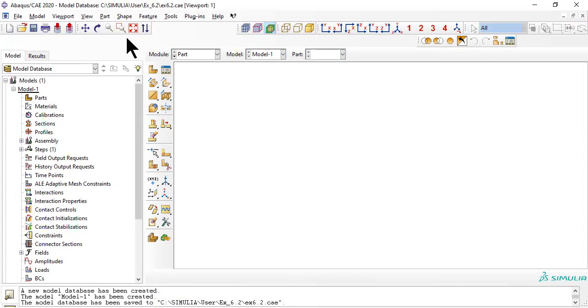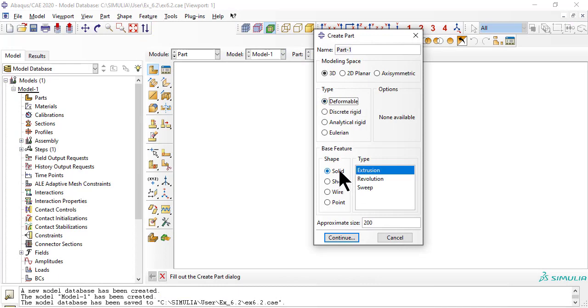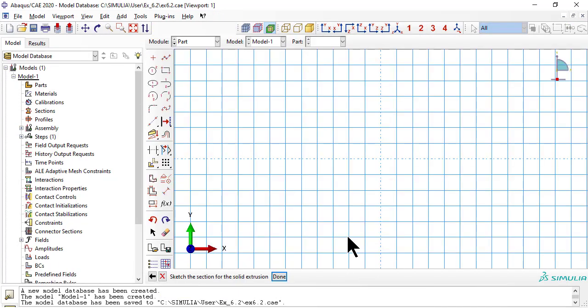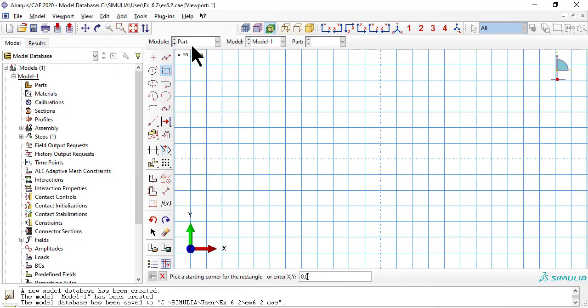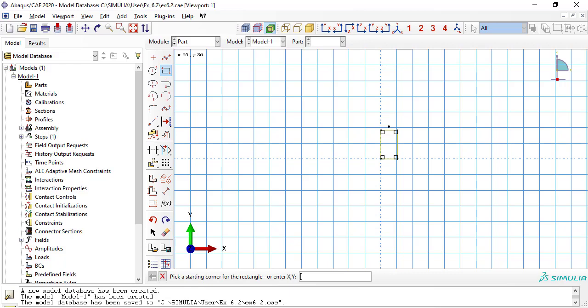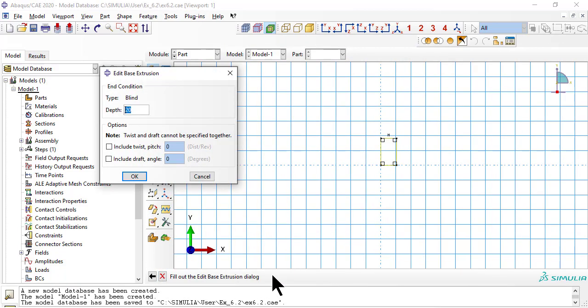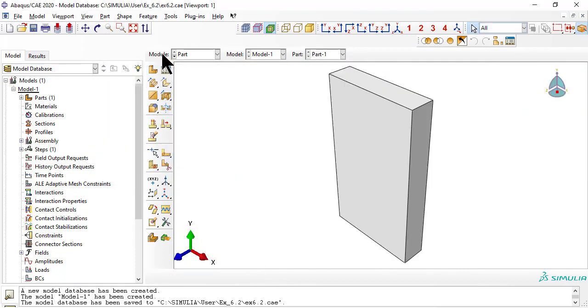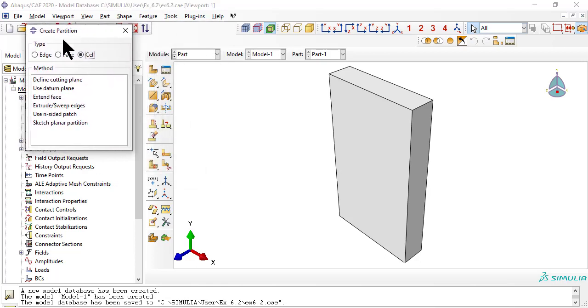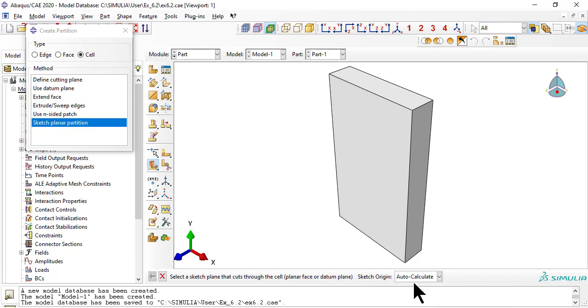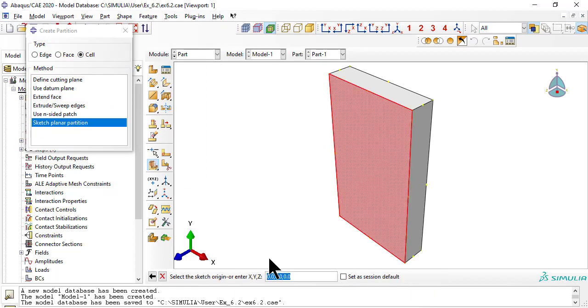To build the part we start with 3D solid extrusion. On the XY plane, we draw a rectangle with dimensions width times height of the RVE, and extrude it with a depth equal to the depth of the RVE along the fiber direction. Now we partition the front face of the cell with a sketch of the cross section of the fibers. The radius of the circle is the radius of the fiber. Then we extrude the fibers through the depth of the cell.